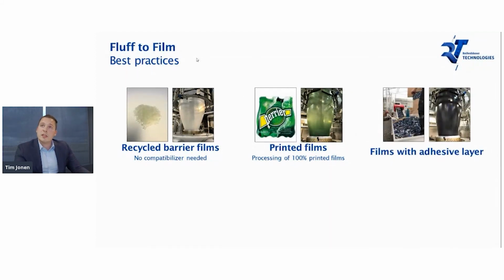The third very successful example was the processing of sticky films with an adhesive layer. As you can see, a trusted customer of ours submitted in-house waste where he didn't know what to do with the materials. We are running the film fluff, as you can see here, directly into the EvoFusion twin screw extruder. And the results of the film, without having to add any process aid or additives, were very surprising and very positive, giving the customer a very efficient and economic way of in-house waste handling.